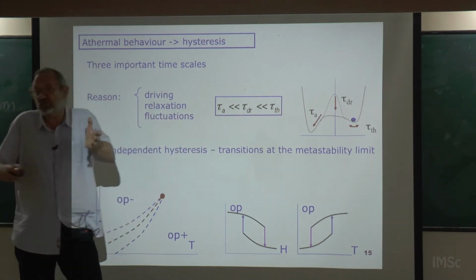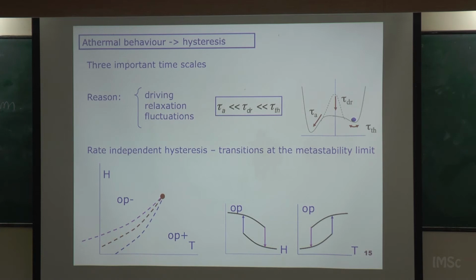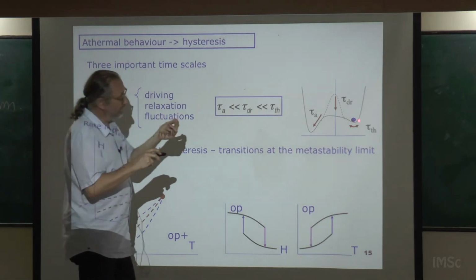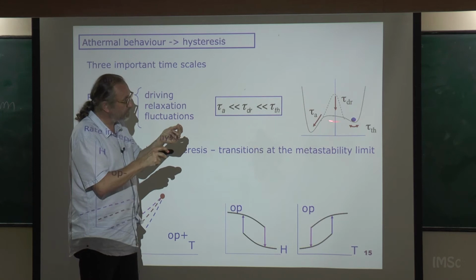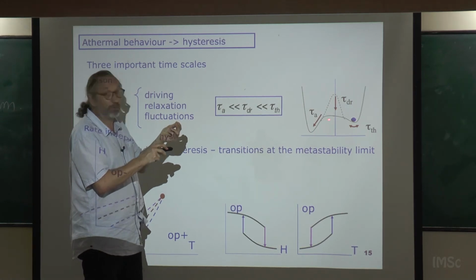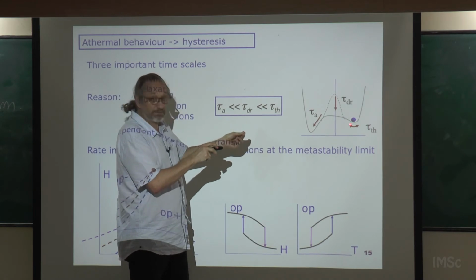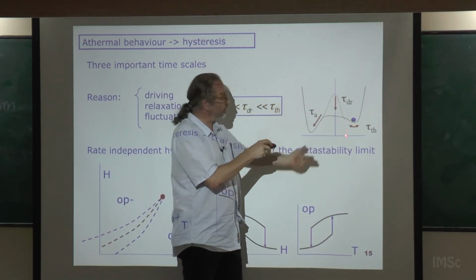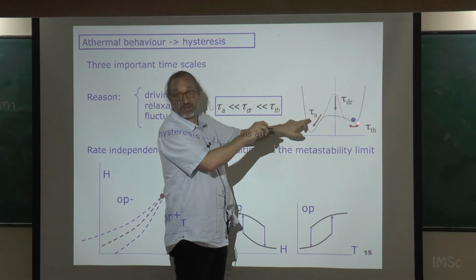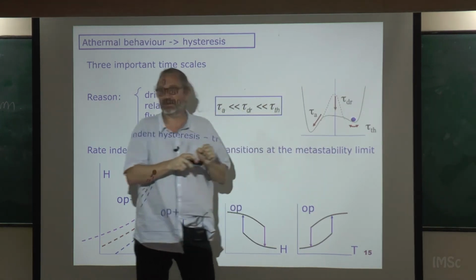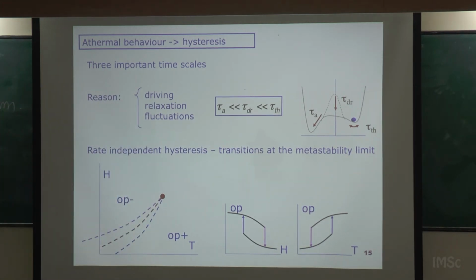The time for thermal fluctuations depends, but typically in solids, if we are at room temperature or below, this is rather short. So we can have even a range of driving rates that are between the two scales. And when you are in this range, you will find that the system doesn't have time to explore this minimum and discover the maxima, because this takes a long time, and you are driving this. So the system does not jump exactly when the two wells are equal. The system jumps when the barrier disappears. And this explains the hysteresis and the metastability, okay?